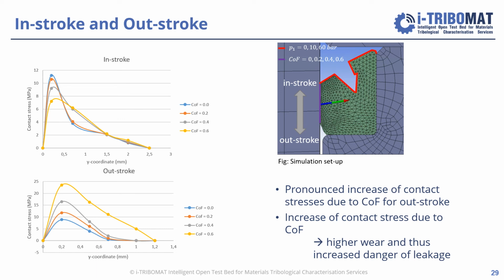Qualitatively, the shape of the curve is the same in the in-stroke mode, so you increase the contact stress to a maximum and then you have a gradual decrease. But interestingly, the maximum is decreasing as you go to higher coefficient of friction values. However, this trend reverses as you move on. So at the coordinate of 1 millimeter, you see again higher contact stresses for higher coefficient of frictions.